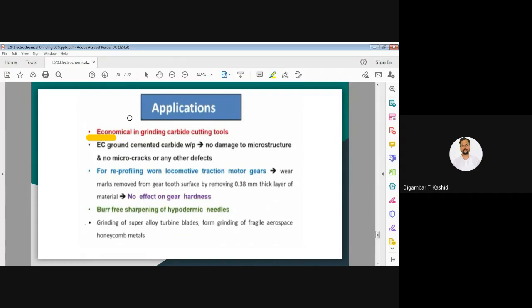Again, electrochemical grinding of cemented carbide workpiece causes no damage to your microstructure, no micro cracks will occur, and there are no other defects. If you go for electrochemical grinding of cemented carbide workpiece, it will not change the microstructure or cause micro cracks. So it is safe for the grinding of carbide cutting tools or cemented carbide also.